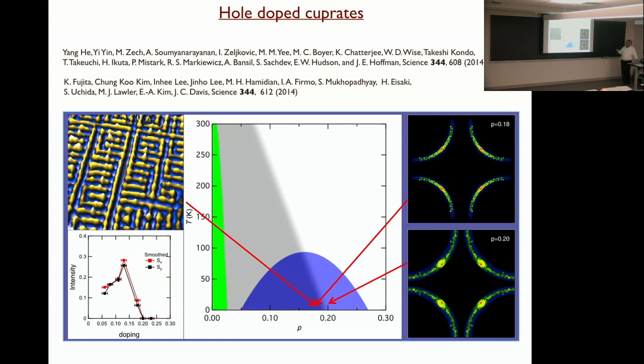Also, if you look at the spatial structure of these modulations, then you see lots of density wave. This is just a view of this as some kind of weak density modulation. You should see here a picture of the copper-oxygen square lattice. These are copper atoms here. And on the scale of a few lattice spacings, there's lots of density modulation on this side, but hardly any on the other side, and so on. So that's one indication.